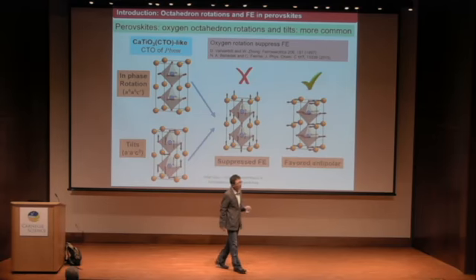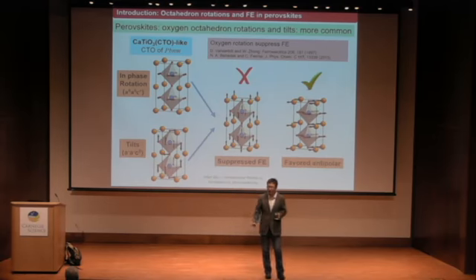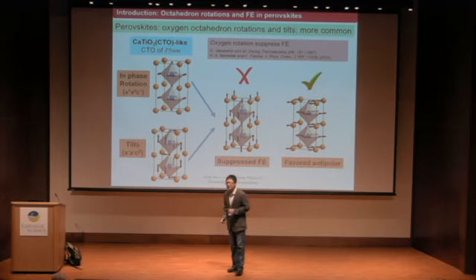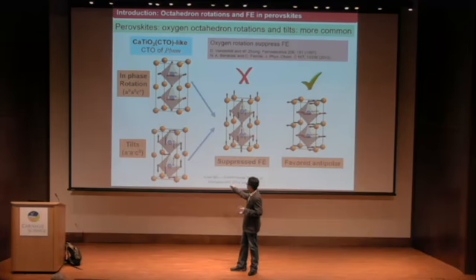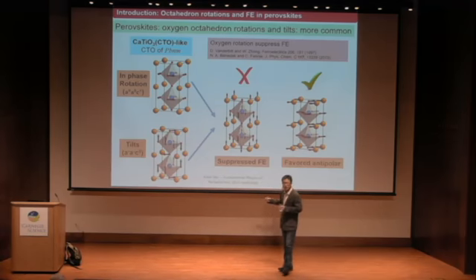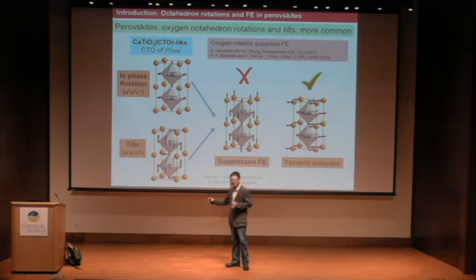This effect was recently revisited by Craig Fennie and Nicole Benedek, and they found that in addition to the in-phase rotation and tilt, this distortion pattern allows the X-point mode, which is an antipolar distortion, to develop. Once this antipolar distortion develops, the ferroelectricity is, of course, suppressed.